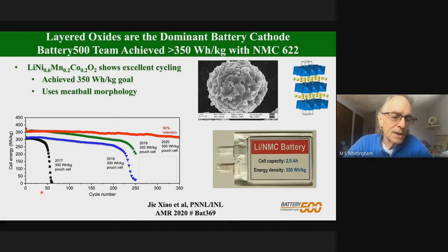So the project started late 2016. So by 2017, we'd got about 40 cycles at 300 watt hours per kilogram. 2018, we'd got up to over 200 cycles, also at 300. By 2019, we're now up to 250 cycles, but now at 350 watt hours per kilogram. And today we're over 400 cycles at 350 watt hours per kilogram. So it's continuously improving.